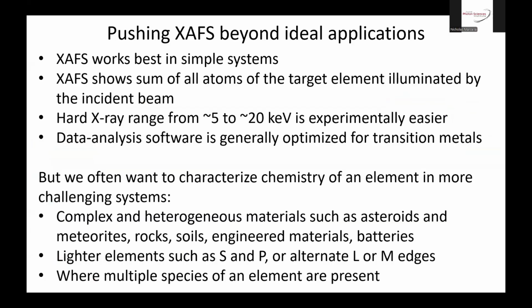So I'm going to talk about pushing XAFS beyond the ideal applications. As Anatoly pointed out in his seminar recently, XAFS works best in simple systems where things are well behaved, primarily because XAFS shows the sum of all atoms of the target element that are illuminated by the beam. So if you have more than one species or population there, you see everything. It gets complicated. Also, hard X-rays typically range from 5 to 20 kilovolts for XAFS experiments.